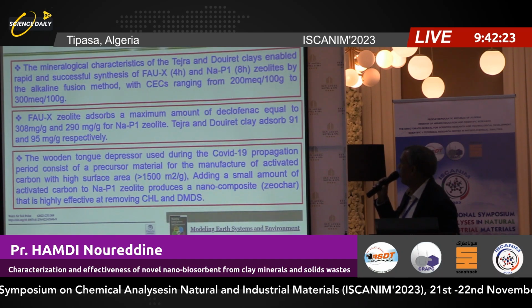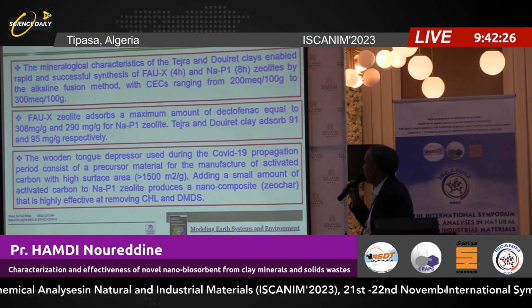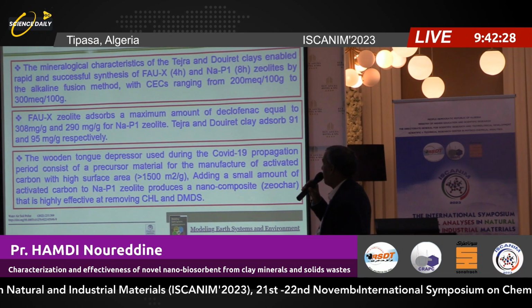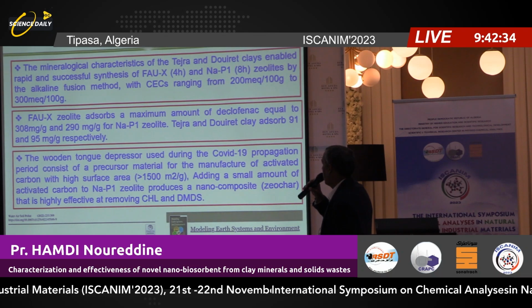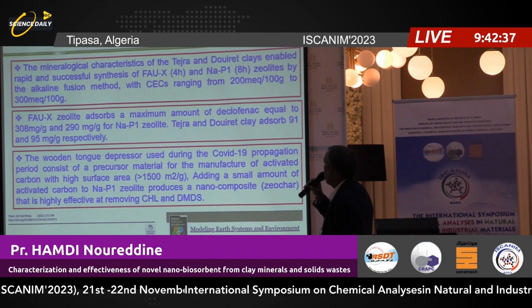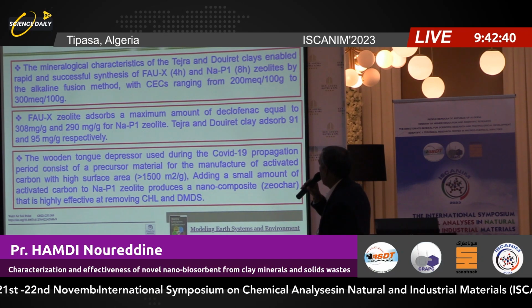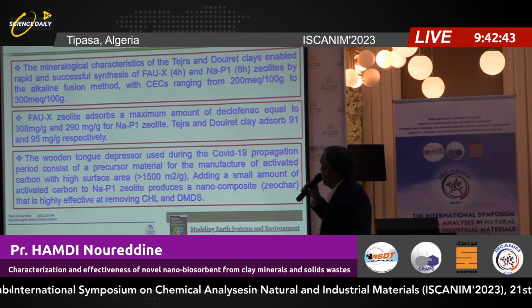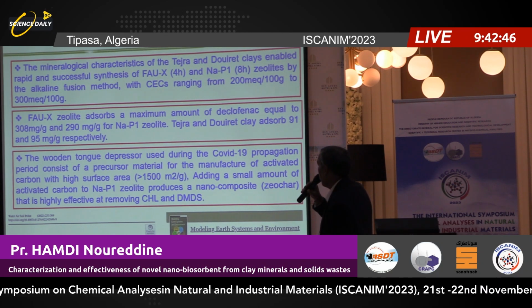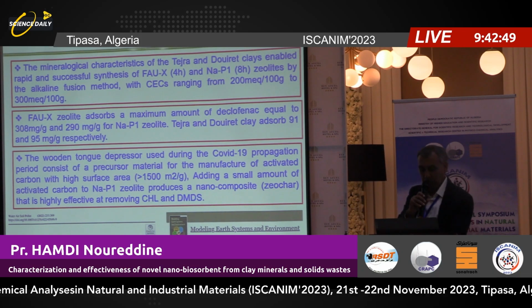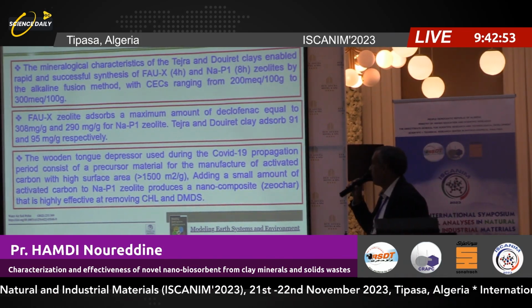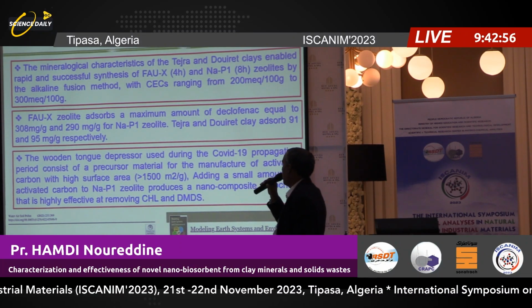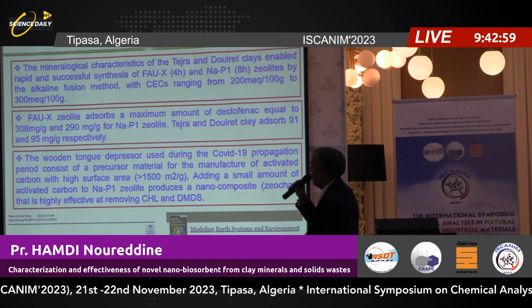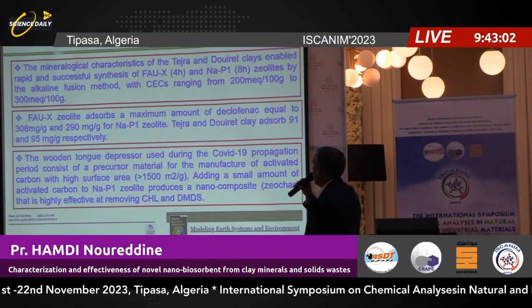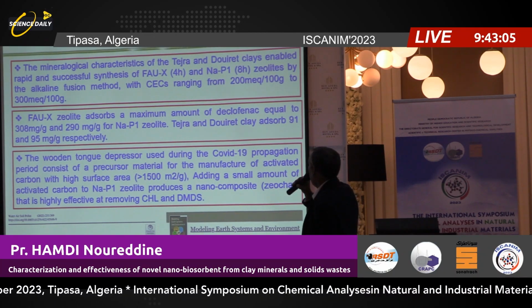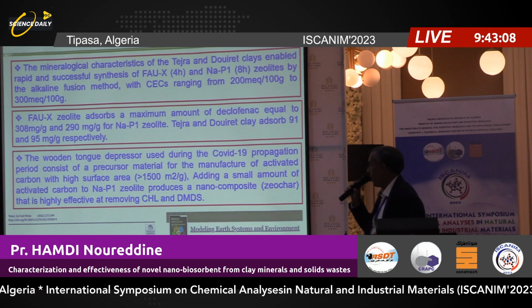As a conclusion, the mineralogical characteristics of the Tejra and Douiret clay enabled rapid, successful synthesis of faujasite X in only 4 hours, and zeolite P in only 8 hours, by alkaline fusion, with an exchange capacity that is very high, more than 200 milliequivalent per 100 grams. The second conclusion, the faujasite zeolite adsorbs a maximum amount of diclofenac equal to 308 milligrams per gram, which, compared to the clay minerals Tejra and Douiret, is very low for the clays compared to the zeolite.